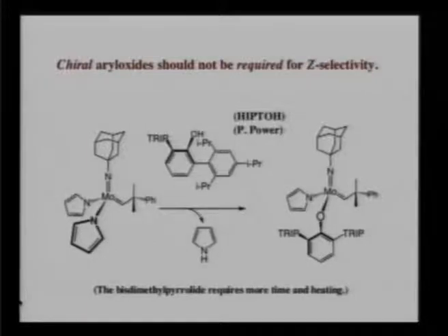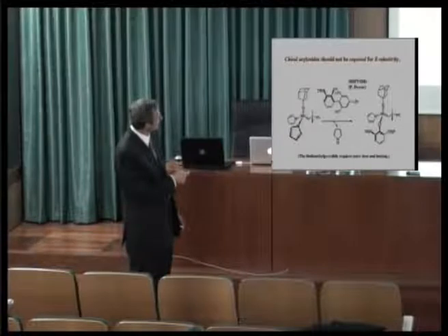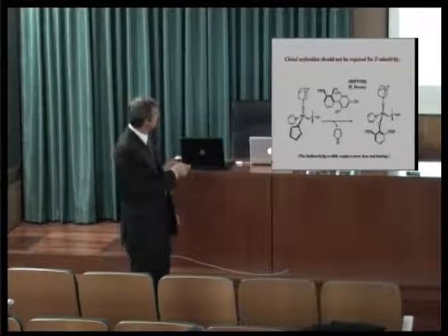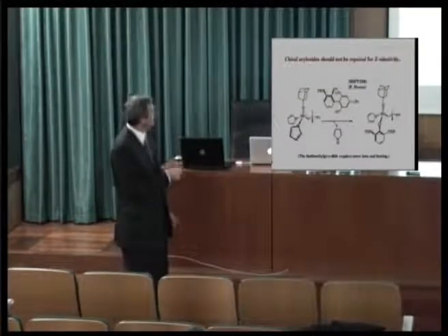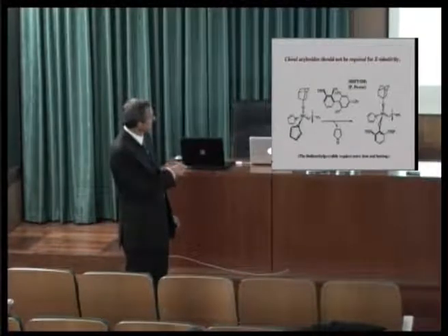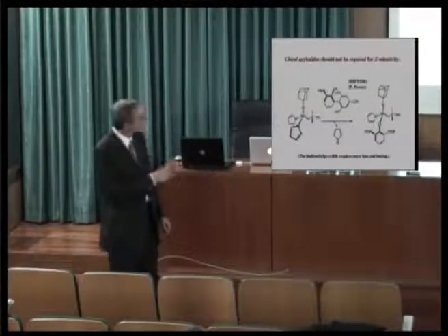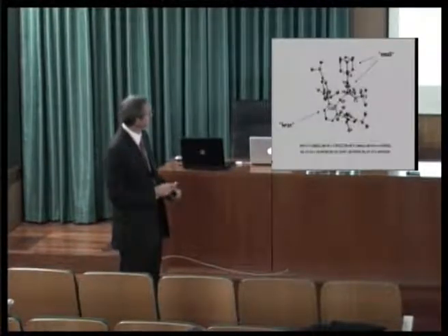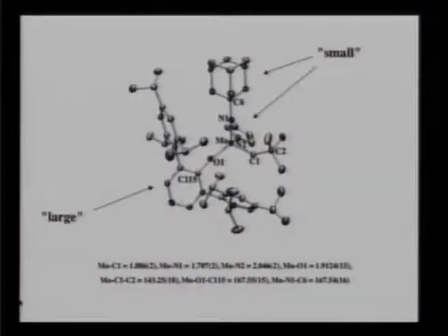Phil Power is at UC Davis in the United States, and he makes very crowded ligands of all sorts. And he made this extremely bulky phenol. This is what I call a hexaisopropyl terphenol. So it's substituted in the 2 and 6 positions with 2,4,6-triisopropylphenyl. This ring is turned perpendicular to that ring and does not rotate readily. So this is a very bulky group, as I'll show you. So it's easy to react this phenol with a bispyrrolide and obtain a new non-chiral, now large, small combination of phenoxide and imido group. This is the crystal structure of the neopentylidene version of that, a large, small combination, and you can see just how large this is.